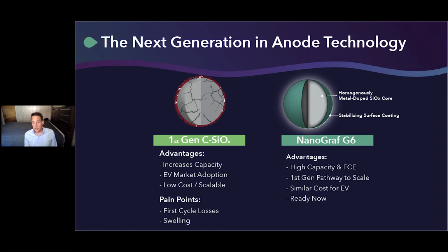So what we've been able to do is develop a unique process to where we could dope the core of the material with lithium homogeneously. And again, our real expertise is in surface coatings, and we've developed a number of special coatings that complement this dope technology so that, again, we can achieve the same capacity that has always been there with silicon oxide, but we've improved the FCE up to 90%, still using that manufacturing pathway that we already know has been scaled, and a cost pathway that we know is going to be attractive for EV OEMs. And unlike pure silicon and solid state batteries, it's a technology that's ready now.